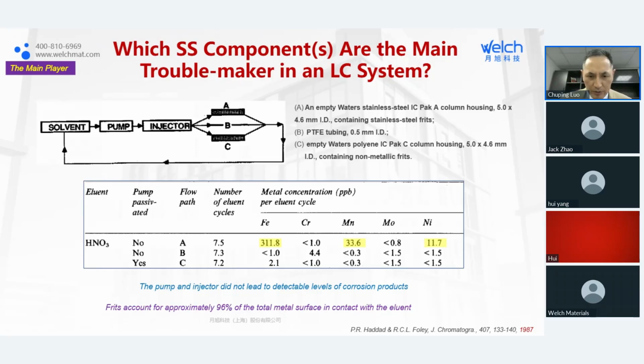The setup here: A is the empty column tube with the frit. The B path is just a PTFE tube. So by looking at B, anything contributing to the ion concentration is contributed only by the system, not by the column anymore. By comparing A and B, we get a sense of which one contributes more. You see in the table that in A, the manganese, nickel, and all these ion concentrations are very high. But if you look at B, it's barely there.